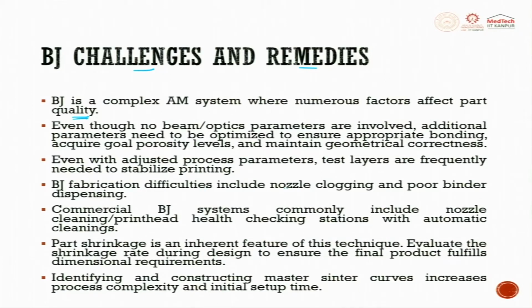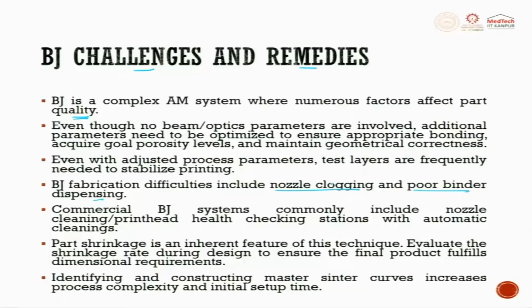The fabrication difficulty includes nozzle clogging and poor binder dispensing. Nozzle clogging is a very big issue. While printing itself, if the nozzle gets clogged, then your print fails. In the FDM process also, if you do improper selection of material or process parameters, there is always a nozzle clog. The moment there is a nozzle clog, further printing will not happen and the entire part will get damaged. So, binder jet fabrication difficulties include nozzle clogging and poor binder dispensing. Commercial binder jet systems commonly include nozzle cleaning and print head health checking stations with automatic cleaning.